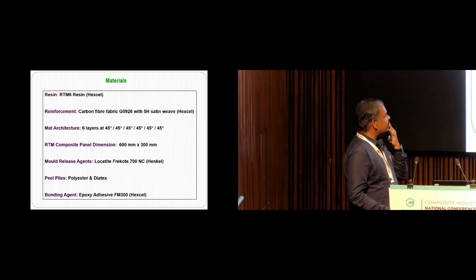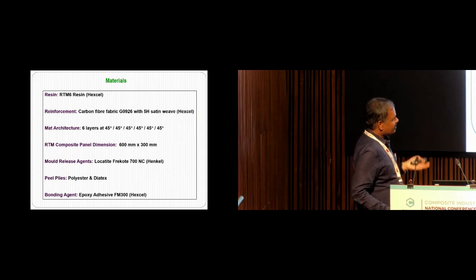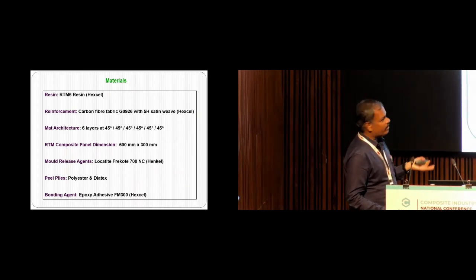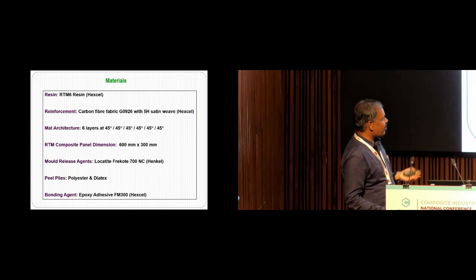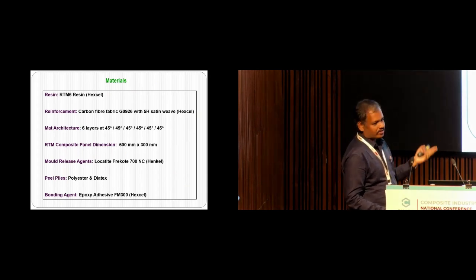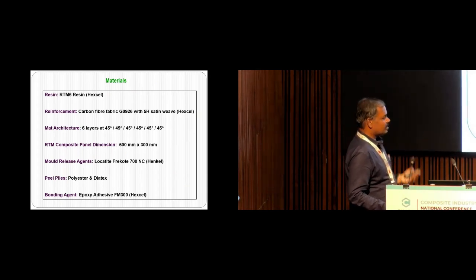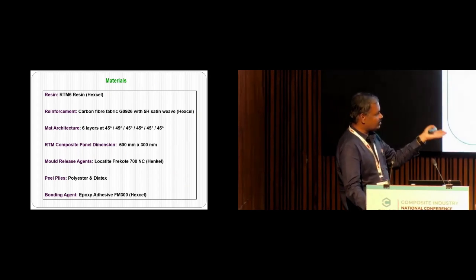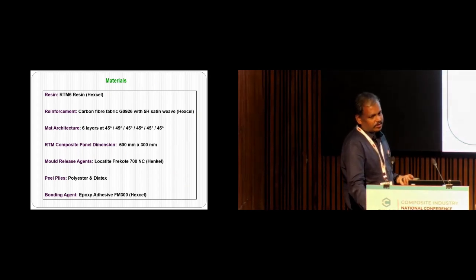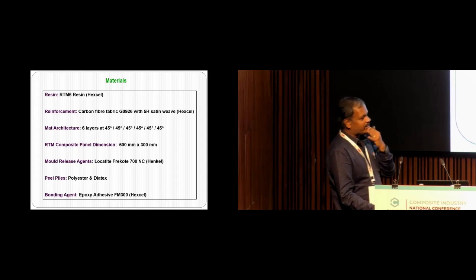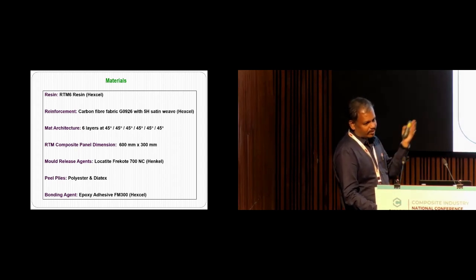The mold release agent is Loctite Frekote, which is supplied by Henkel, and the peel plies are polyester and Diatex. These two brands were used, and the thin film used is epoxy adhesive FM 300. So these are very, very important parameters. For this also we took consultation from Airbus.